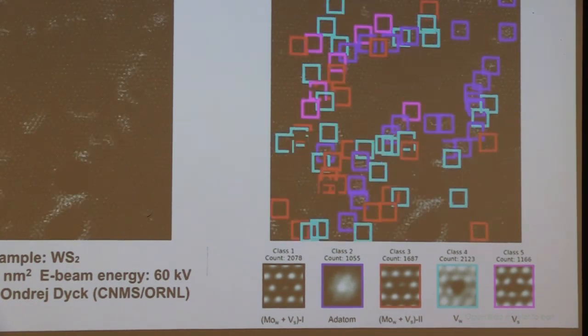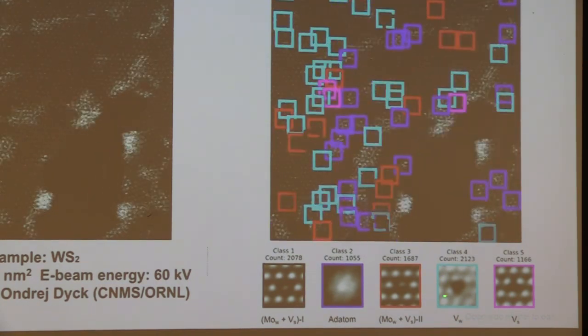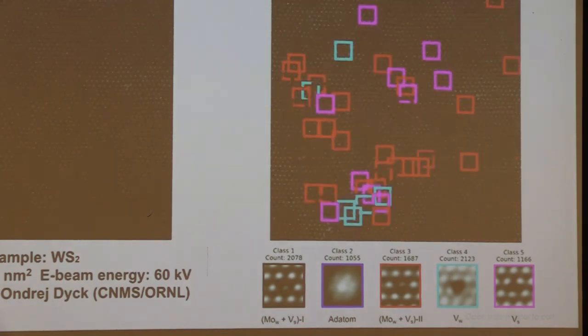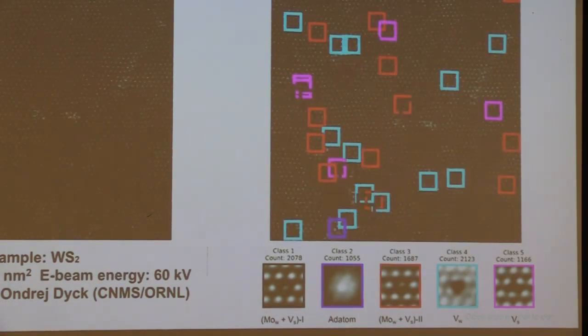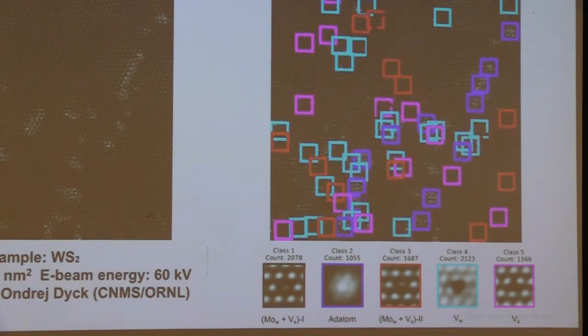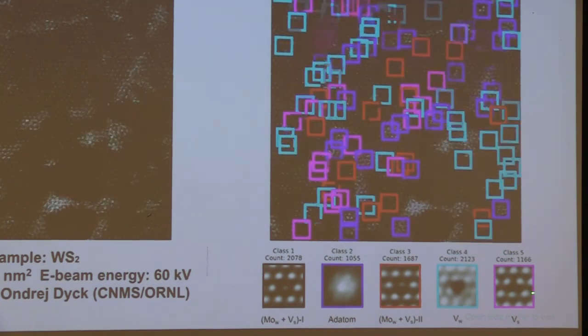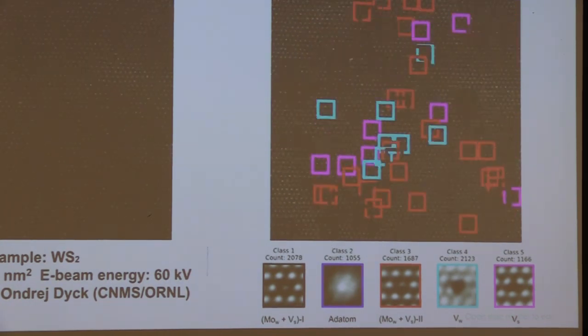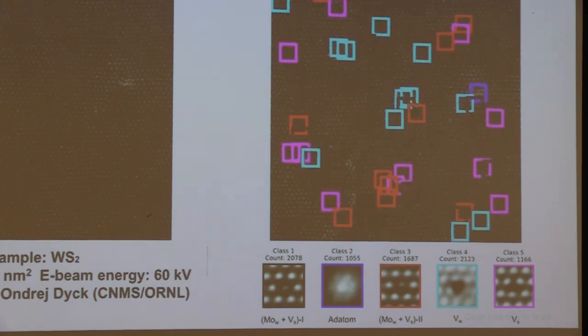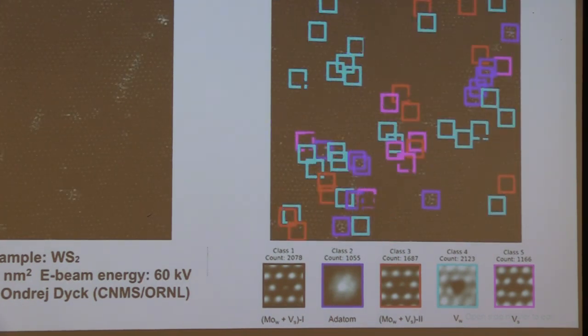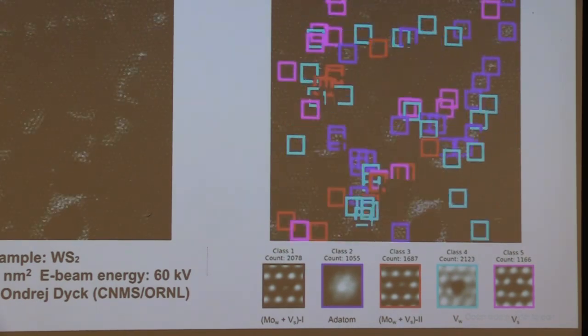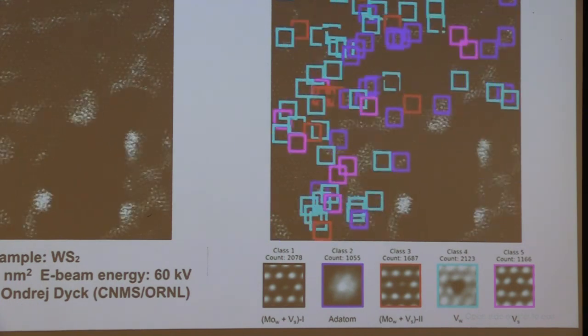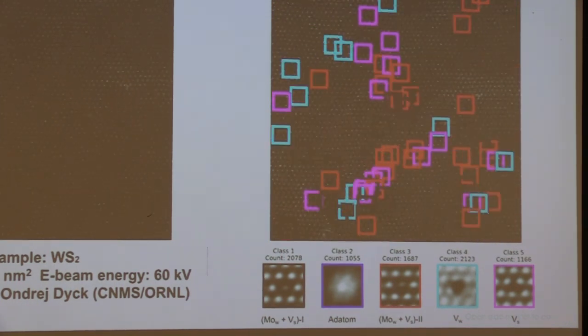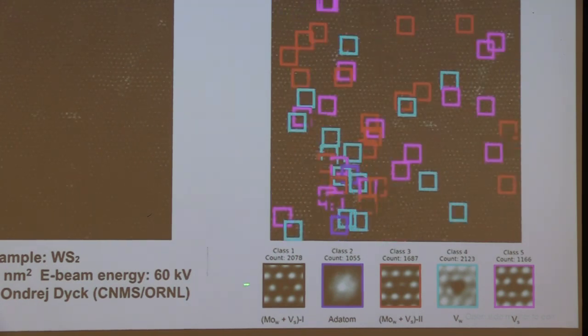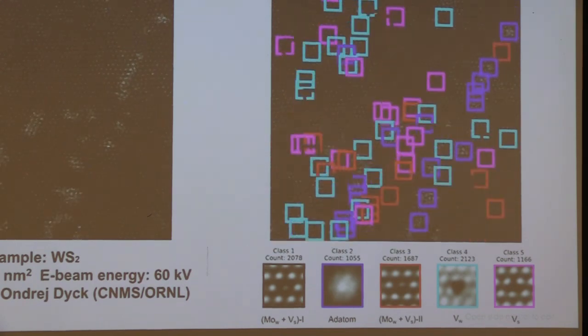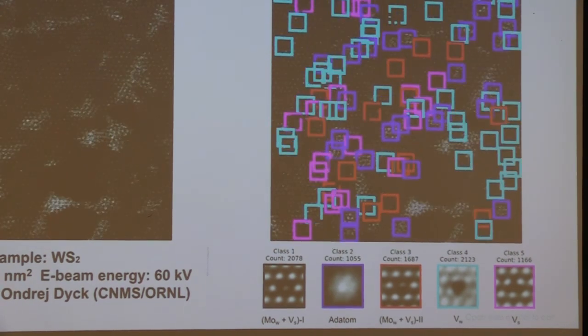And then you have ones where you actually just knock the atom out and there's nothing there, a vacancy. So the atoms that are easiest to knock out are the sulfur, the chalcogenide ones. They're easier to knock out than the metal. Much easier, much lower energy to knock out. So these are sulfur vacancies, and there's a couple classes of these sulfur vacancies. So there's basically only 5 types of defects occurring in this image that was found by the neural networks. And that seemed to correlate quite well with what we can see from the images and do with the tedious by-hand analysis. So it was able to identify these, classify them, cluster them correctly on the fly. And over here on the right, you're seeing these different defects, how they move over time. Now, I challenge you to tell me the diffusion coefficient of any one of those boxes.